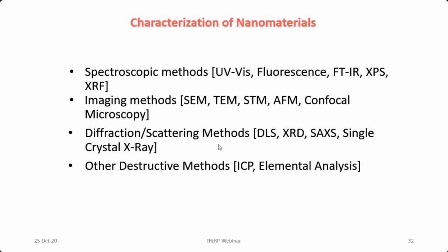But when the sizes are measured through DLS for a particular nanoparticle, say silver nanoparticle, I am preparing using PVP as a kind of capping agent. So when I measure the size with SEM, and when I measure size with DLS, there could be difference, because in SEM you are measuring essentially dry nanoparticle on the substrate of the SEM grid. But in case of DLS, you are measuring it in a solution. So essentially, what sizes you are going to get, they are actually hydrodynamic volume or hydrodynamic radius or diameter of your nanoparticle you are getting through DLS. And it could be different. Like sometimes DLS sizes are always on a higher side compared to SEM sizes, and that is why also many times for absolute sense people tend to ask for SEM data compared to DLS.